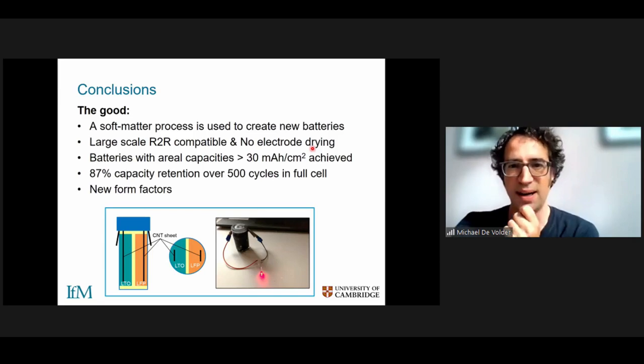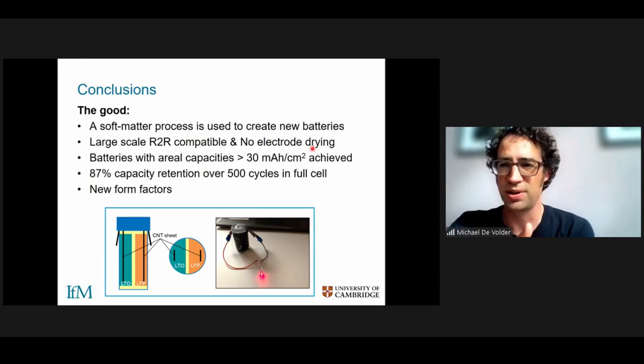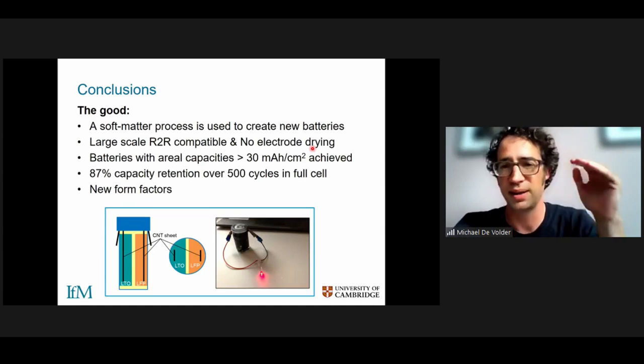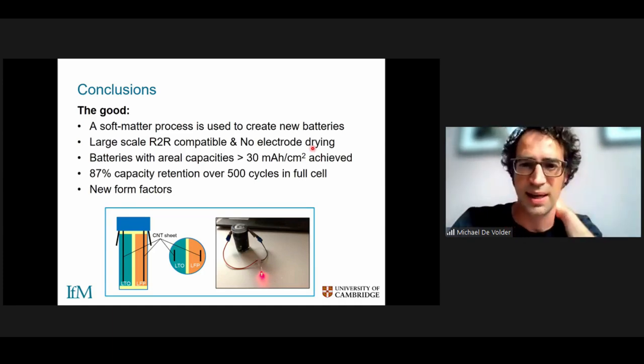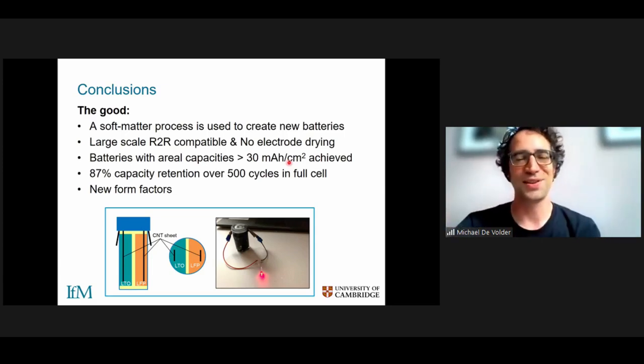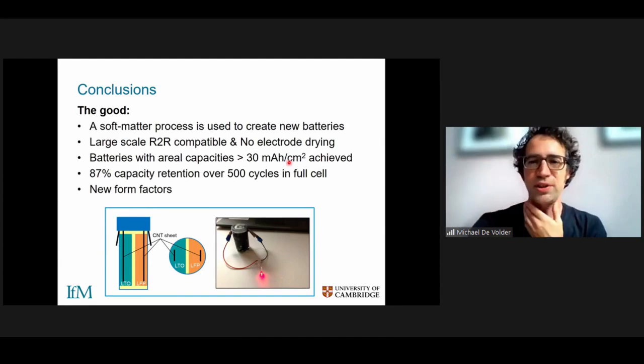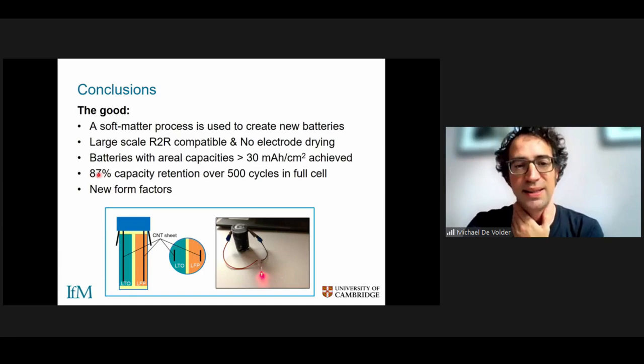And interestingly, because we are using a phase segregation process, we don't need to dry our electrodes, which, as I mentioned at the beginning of the talk, is a time-consuming and energy-intensive process. In our case, we only need to cool down our electrodes from 150 degrees to room temperature, which is less energy-intensive. So we've been able to create batteries with very high areal capacity, so we can store a lot of ions on a small footprint. And we've achieved very good stability, so 85%, 87% capacity retention over 500 cycles of charging and discharging the cell.